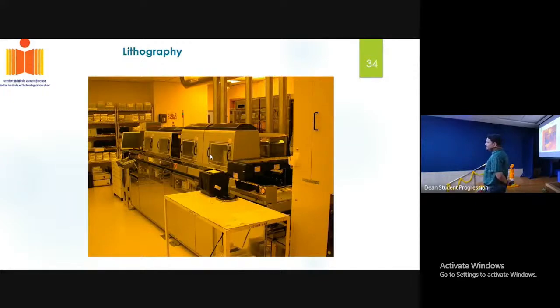Using the photolithography, you can write the structures up to 50 micrometers or 1 micrometer maybe, and using the e-beam lithography, you can write up to 10 nanometers, because it's based upon the wavelength of the source that you are using. So the light diffraction limit will be up to the order of micrometers. That's why you are able to write only up to micrometer levels using the UV light. The electron wavelength is much less than the light. That's why you are able to write the smaller structures, nanometer-size structures, using the electron wavelength.